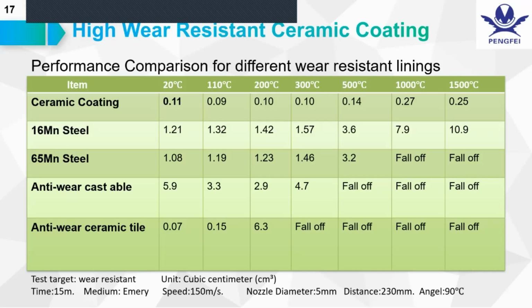You can see after 300 degrees, the ceramic tile, which is attached by glue, may fall off. The castable's wear rate reached 4.7, while ceramic coating still reaches about 0.1, which is very stable, with stable performance under different temperatures as well. So ceramic coating is a very good material, working stably at different temperatures. Manganese steel at 300 degrees has even 10 times more wear rate, and manganese steel is also expensive. Okay, later we will see the difference between castables and coatings.